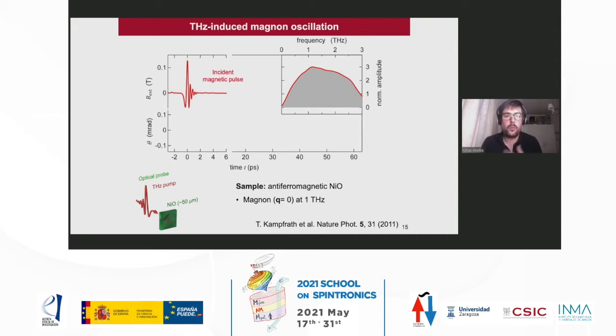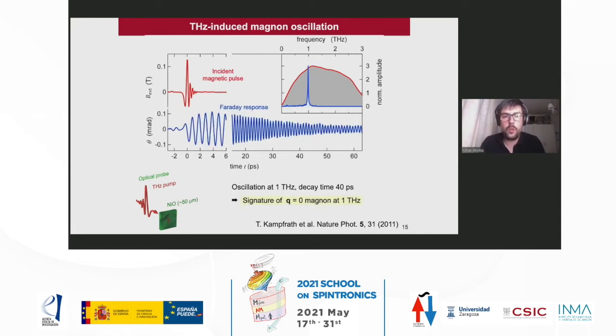What they observed after applying this incident magnetic pulse is that they could induce a very fast precession of the magnetization, with a frequency of around 1 terahertz and a decay time of 40 picoseconds. This is a clear signature of a q equals 0 magnon at 1 terahertz.